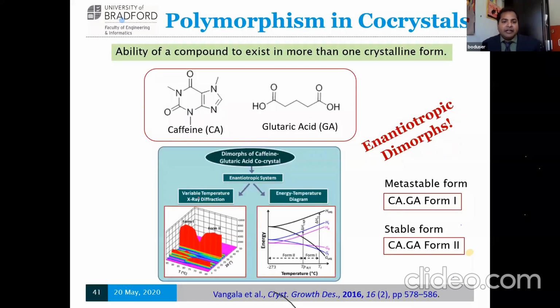Again, we have taken here the caffeine glutaric acid system. We have investigated the polymorphic behavior of this system. What we found out was there are two polymorphic forms possible for this co-crystal. One is form 1, which is the metastable form. Form 2 is the stable form. We did some in situ X-ray diffraction studies to investigate the phase transformation and the transition temperature. We did some Rietveld analysis.